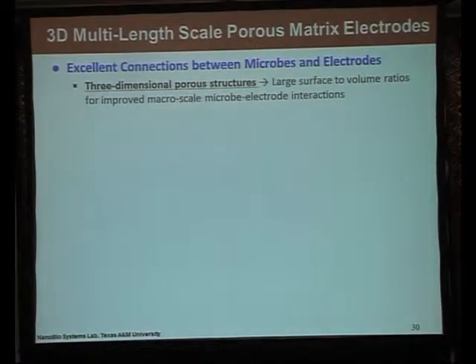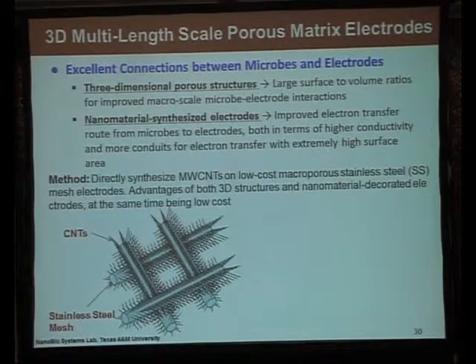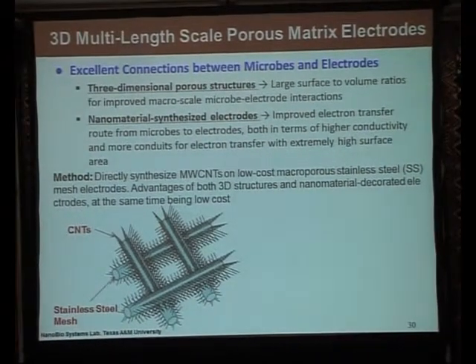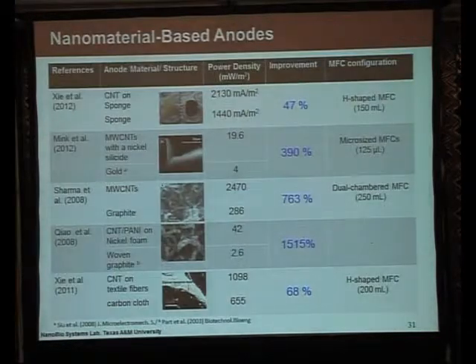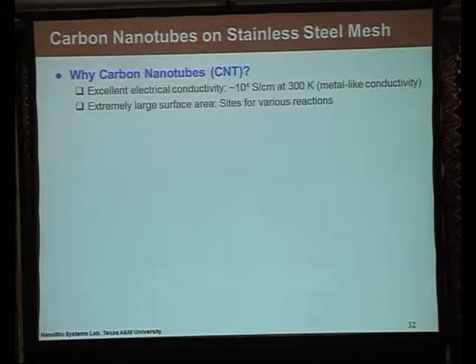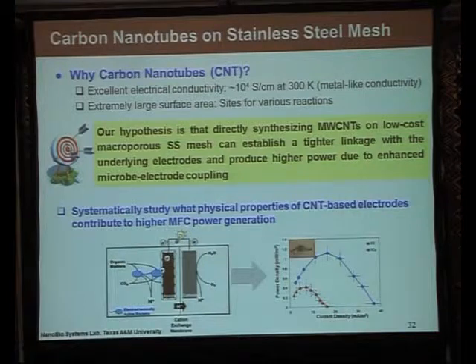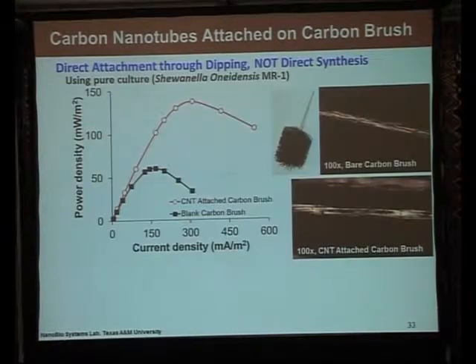Now, using this screening system, we are screening the different materials that we have developed. First, we start out with a 3-dimensional porous structure, such as stainless steel mesh, and our method is directly synthesizing carbon nanotubes on this low-cost stainless steel material. We are obviously not the first to make a nanomaterial-based anode. However, our approach is very different.